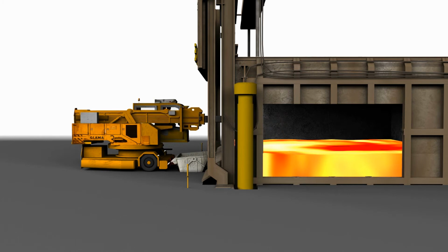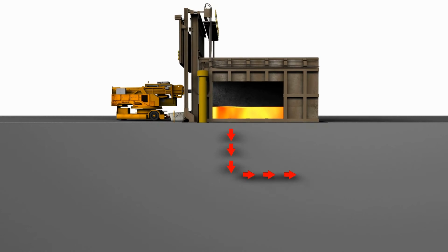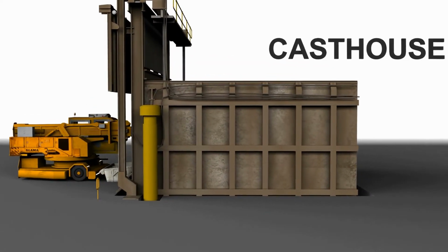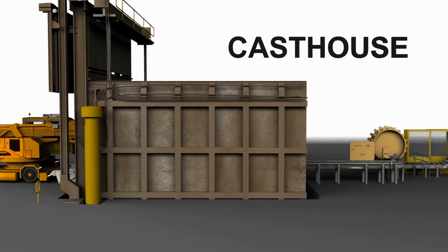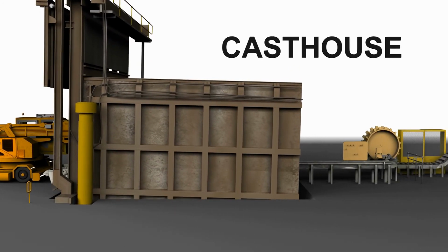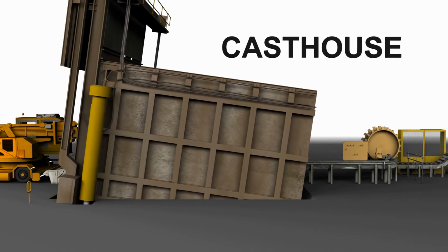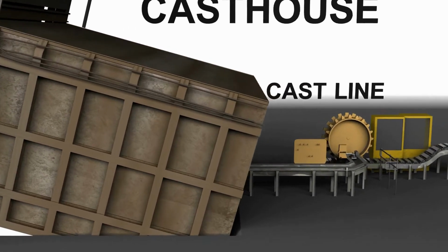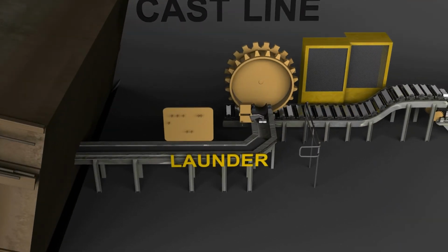Samples of molten aluminium are obtained at this stage using a special spoon and poured into portable molds. These samples are barcoded with batch information and taken to the laboratory for analysis. When the holding furnace is full, hydraulic jacks tilt backwards and the aluminium runs into a launder, or trough, and flows to the casting wheel. Samples are again taken as the metal is cast.